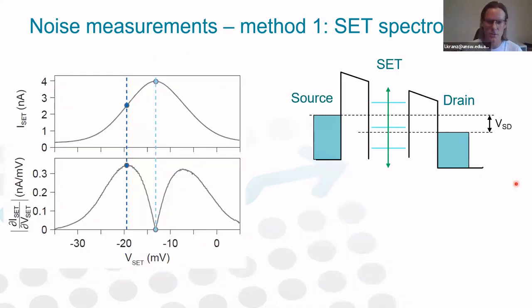Okay, so now I zoom into one of these Coulomb peaks. What I'm showing here is again one of these Coulomb peaks. And what I want to do now is tune this charge sensor to its highest sensitivity so that I'm going to be sensitive to any fluctuations that are intrinsic to the device. So how do we find the highest sensitivity point? Well, we calculate the derivative dI/dV, which is shown here at the bottom, and we find that the maximum sensitivity point is found here at the side of the peak, which means that if you change the voltage slightly, you get a big difference in tunneling current.